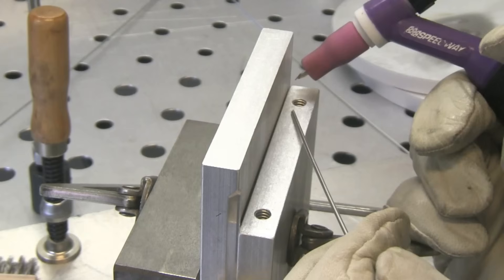Here's a good example of where a small aluminum weld would be required, and it's not that easy to get a small fillet weld on a thick piece of aluminum like this. But it could be called out for on a drawing because of the hole right up next there, and you need to get clearance. So to get the weld started, sometimes you have to stab it and kind of pierce through the oxide film.